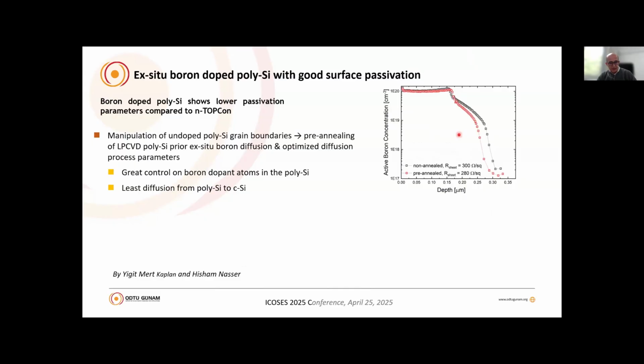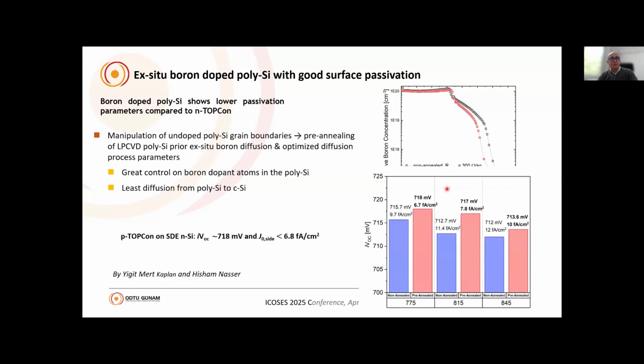Doping has been optimized, and we have nicely optimized the front surface doping, I mean the doping of the poly layer, and we have developed some new recipes for this by including some pre-annealing steps, etc. This is already published, so if you are interested, just let me know. I can send you the paper. With this P poly layer on the front side, we have reached quite high implied VOC values and low recombination current values.